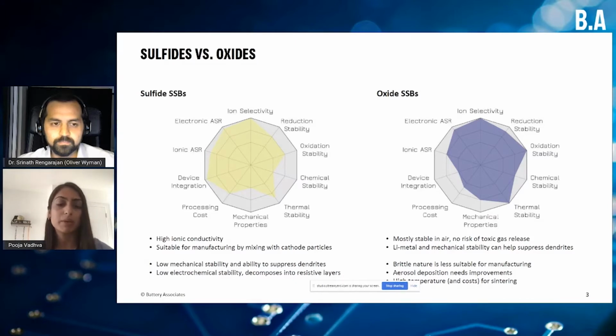So that's very nice for manufacturing and processability. They have very high ionic conductivity, so that's very good for charging. The lithium transport throughout the solid electrolyte is very fast. The main issue with sulfides is basically their electrochemical stability against the lithium anode, mainly the electrochemical window. When you're cycling a cell from 0 to 4 volts, or when you use high voltage cathodes up to 5 volts, there is degradation with the lithium metal. The sulfides get reduced and form resistive compounds at that interface. And that's one of the main performance-limiting areas for sulfides.